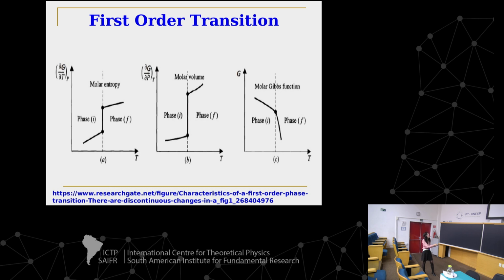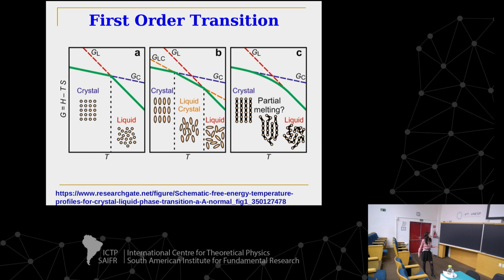That means that the derivative of G with respect to T, that's the entropy, has a jump that I'm representing here. But also, if I draw the same graph, G against pressure P, it will have a similar shape with a discontinuous slope, and that's why the derivative of G with respect to P, which is the volume, also has a jump. This means it's discontinuous in whatever property you're using, volume, and it will be discontinuous in the entropy as well.